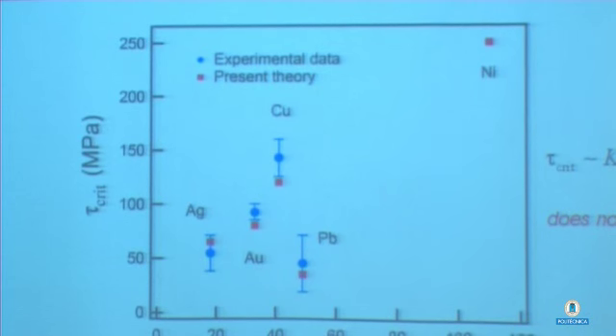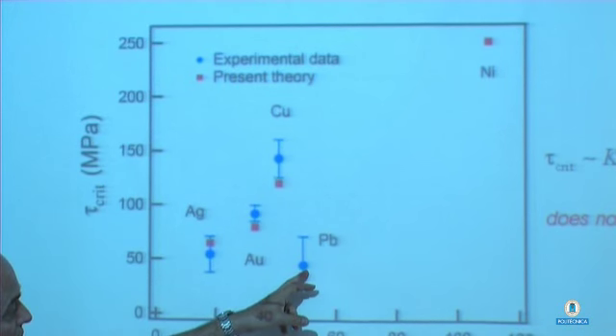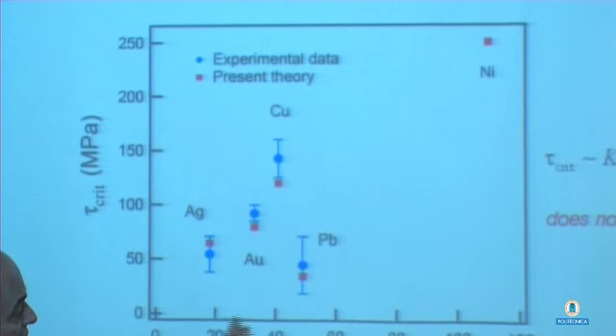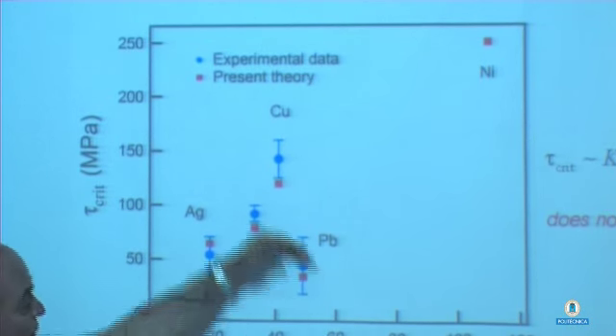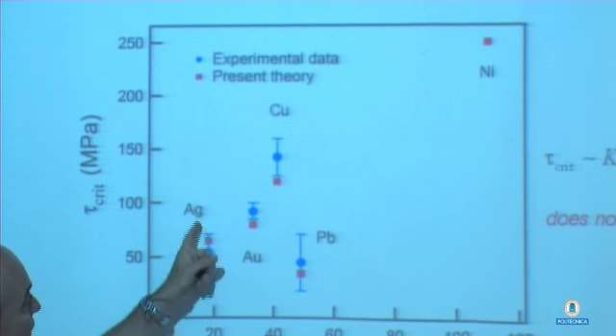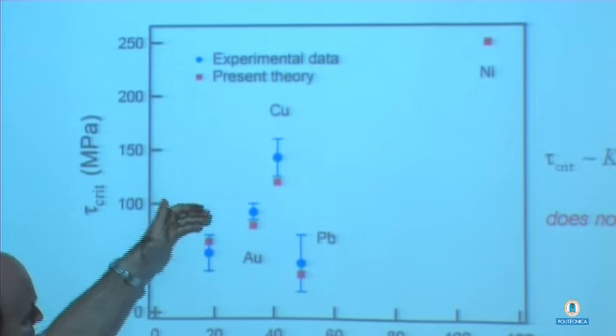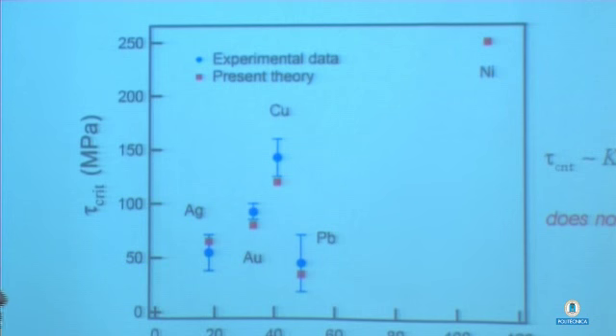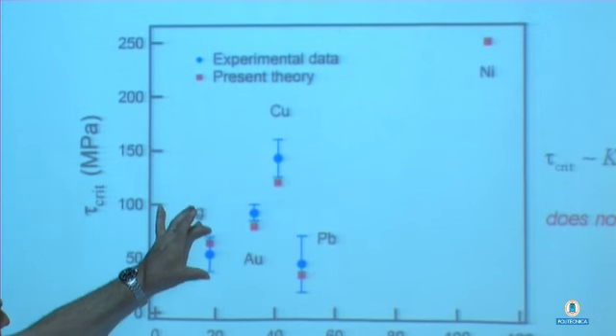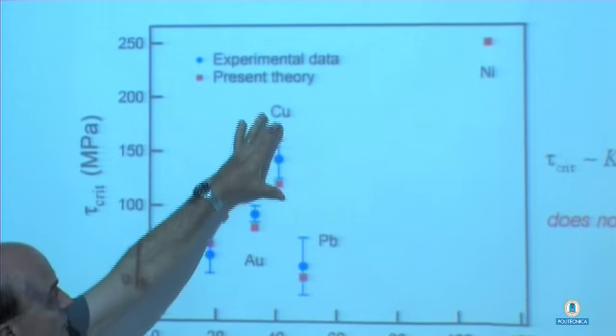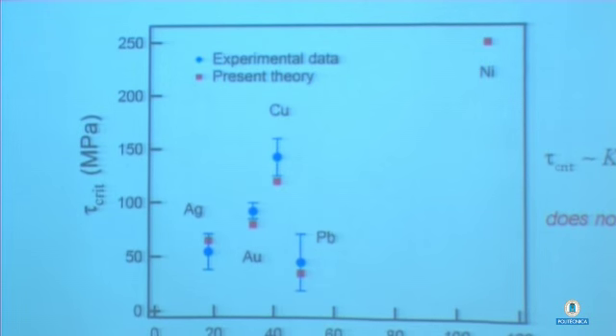It doesn't work. In fact, lead here has a higher ISF, but a lower twinning stress compared to silver, gold, copper. These are the experimental ranges from the literature. There is a variation, and the red are the predictive values. Now, nickel, I didn't show any experimental results. Typically, for a regular coarse-grained nickel, you don't get twinning.